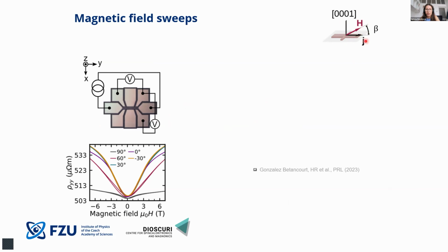This is because there are multiple domains in this compound, and the in-plane component of the field helps us to orient the domains in the preferred direction. So I will show a little more of the magnetic fields, but just so you see that the magnetic field is not perfectly perpendicular, and this is the reason. The longitudinal measurement, the magnetoresistance, shows this sort of even symmetry. There is maybe something small happening here, but it's a relatively conventional signal.